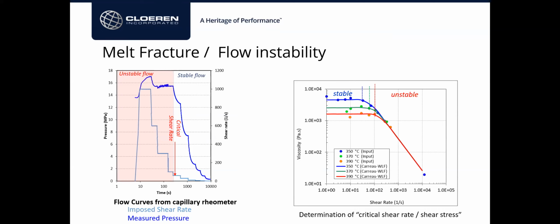Okay. How would you evaluate process aid performance with a rheometer? Well, you could try different compounds, different concentrations. It depends on your goal in the end, but if you're, for example, experiencing melt fracture, you could try to detect where the critical shear rate will be and if there's any influence of the composition. For example, higher concentration of PPA, higher critical shear rate or something like that. You can compare the thermal stability, you can compare the overall viscosity versus shear rate. So there's a bunch of stuff you could do, but those 3 things is basically what I would try.